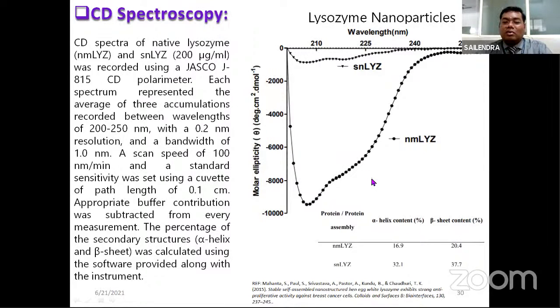So when you put a protein in a stressful environment, your beta content will increase. Now, nanoparticles will always have an increased beta content. The reason being, you are precipitating the protein, and the protein always tries to be in a stable structure. But under the influence of the solvent, the protein precipitates and you get these protein nanoparticles. So whenever you have these protein nanoparticles, you will always see both the alpha helix content and beta sheet content are going to increase in such nanoparticles, whereas the native lysozyme will always have less.